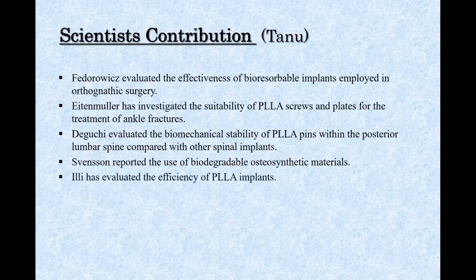Illi and others evaluated the efficiency of poly-L-lactide implants in 32 children aged 11 months to 17 years with 15 cases of craniofacial malformations, 16 cases of neurotraumatological lesions, and 1 case of refixation of an osteochondral flake of the patella. The follow-up time ranged from 3 months to 5.6 years with an average of 3 years. The stability achieved was comparable to that of metal implants. No foreign body reaction or local infections were observed, and it was not necessary to remove any of the resorbable implants.